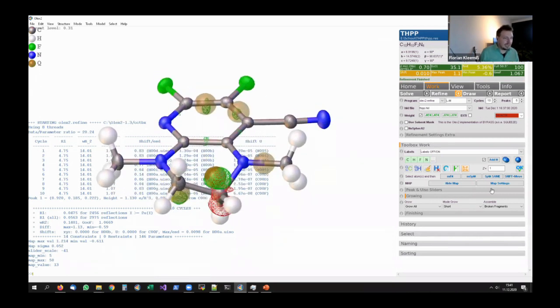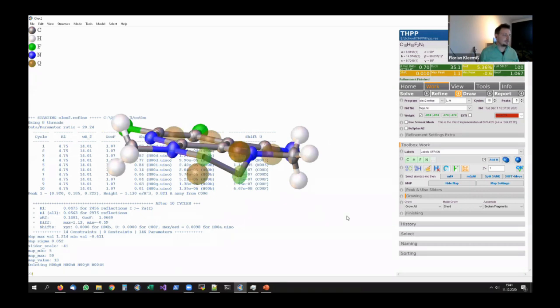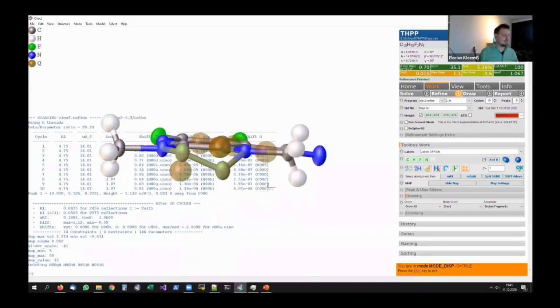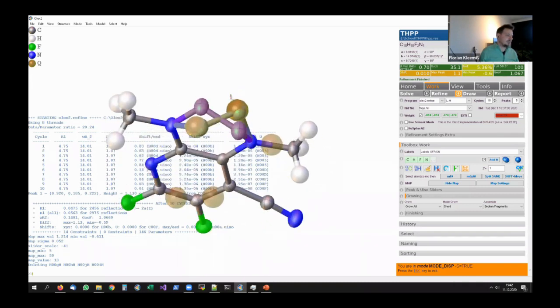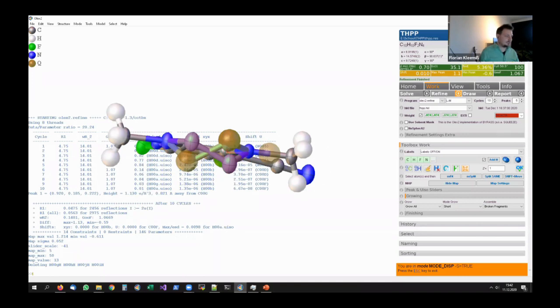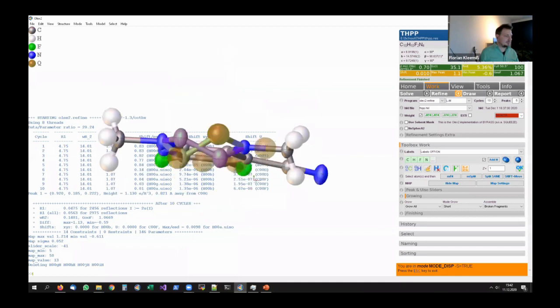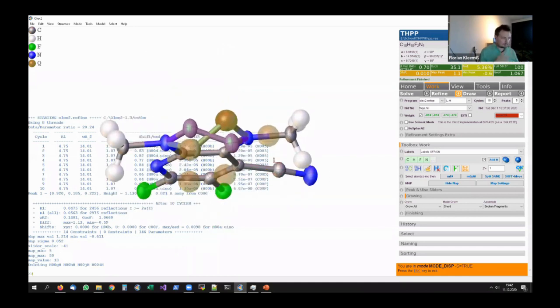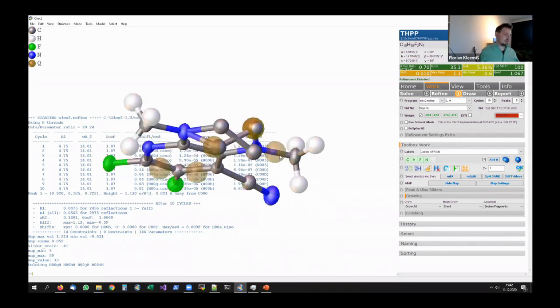So what we need to do is make a disorder model. And this is very easy in OLEX2, in my opinion. First, because usually hydrogens are more difficult to deal with, I delete the hydrogens here. And these two atoms I want to split. So I will use M split here, and then a copy of these atoms is generated on the screen that you can manipulate now. If I click somewhere where there's nothing, I can still rotate my molecule. But if I click here, I can now modify the copy of these atoms. If I hold shift and drag them somewhere around, I can place them where I want. If I just touch them here, I can rotate them. And this basically allows me to fit the disordered component in here. If I'm satisfied with my new disorder component, I can press escape on my keyboard to exit this mode.